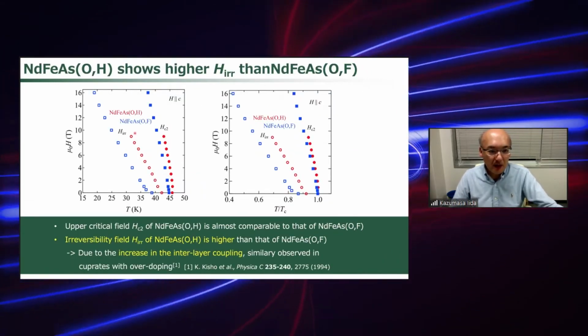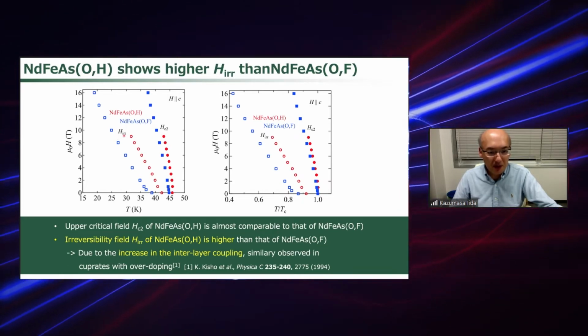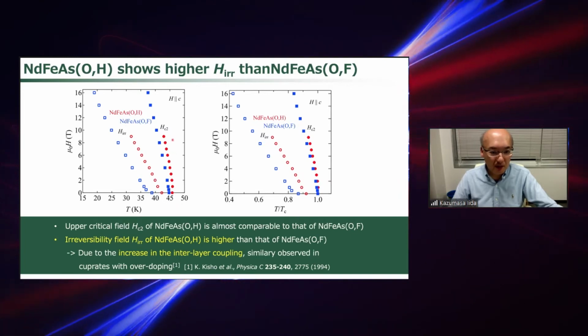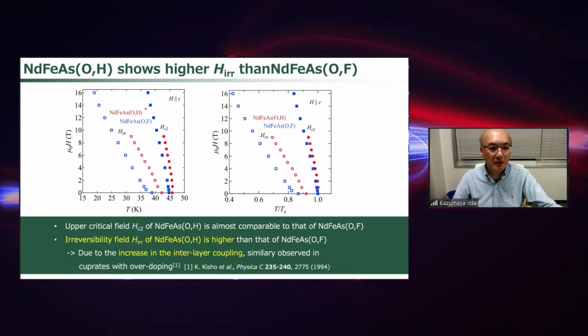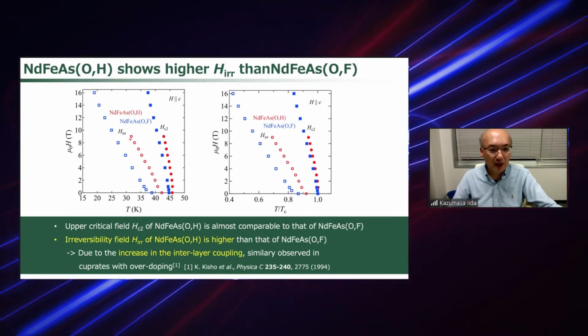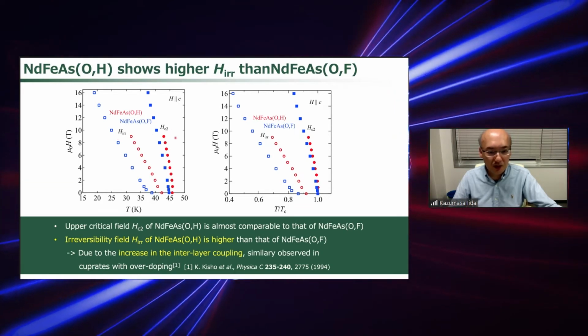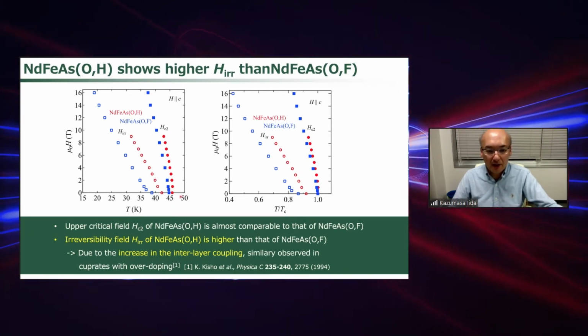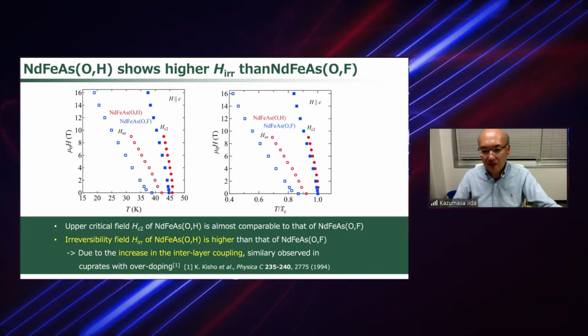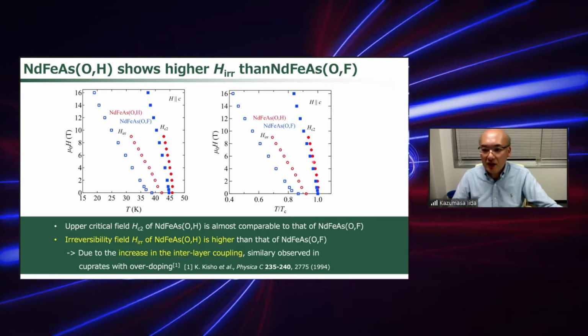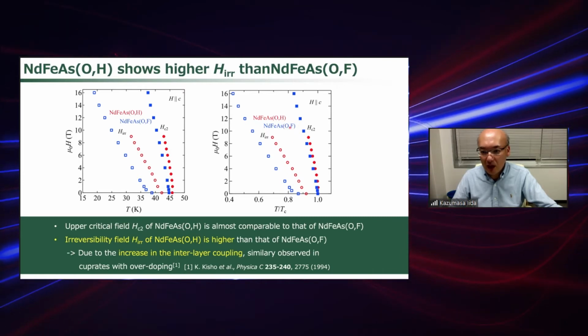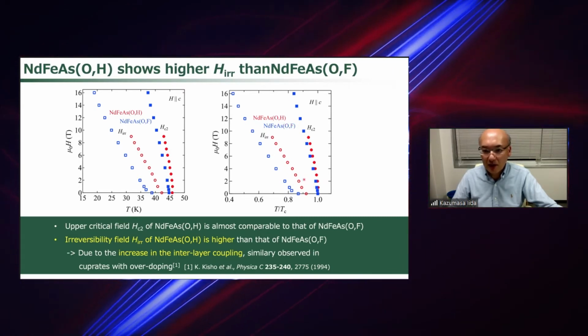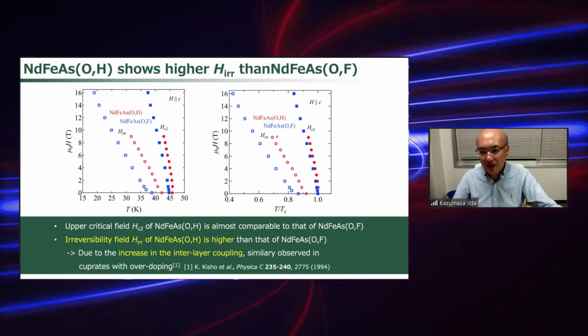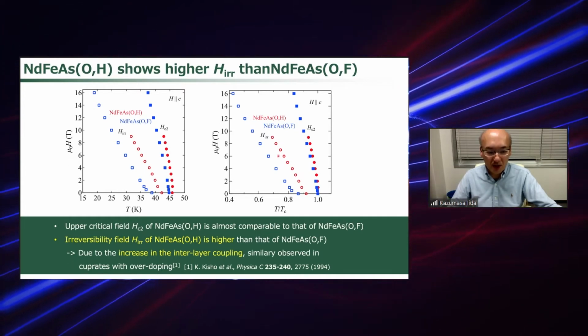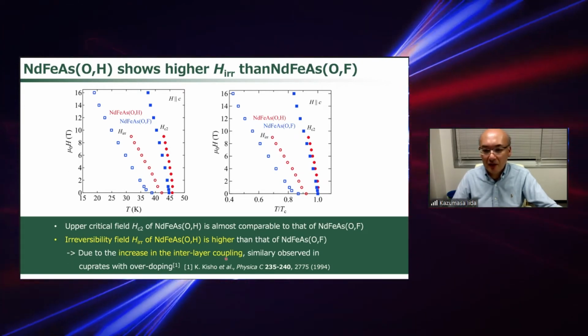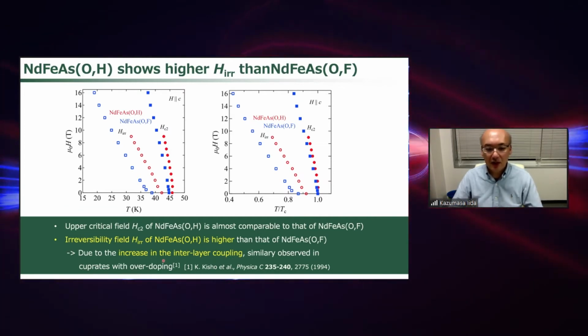We also evaluate the upper critical field and the irreversibility field for the field parallel to the C direction. The red symbols represent the hydrogen-doped samples, the blue symbols are fluorine-doped samples, the open symbols are the irreversibility field, and the solid symbols are the upper critical field. To make a comparison, we replot the data as a function of the reduced temperature. You see that the HC2 for both fluorine and hydrogen-doped samples is comparable, but the irreversibility field is higher than that of the fluorine-doped samples. This is because of the increase in the interlayer coupling, which is similarly observed in the overdoped cuprate samples.